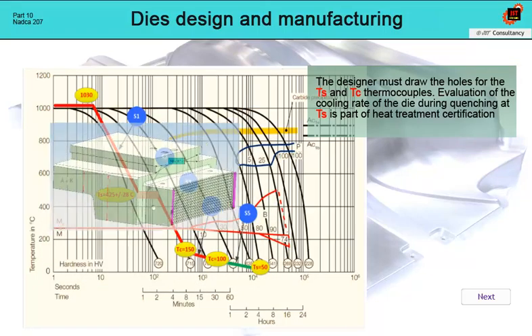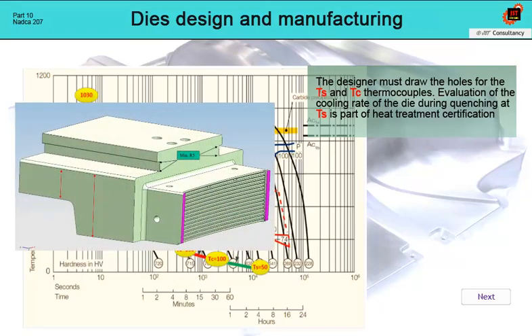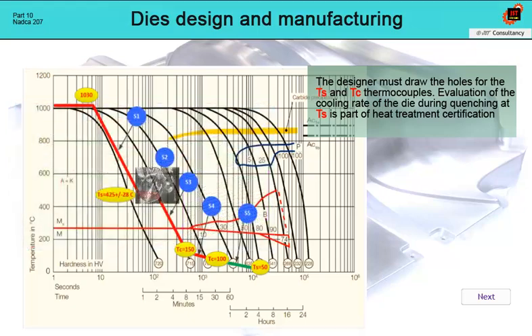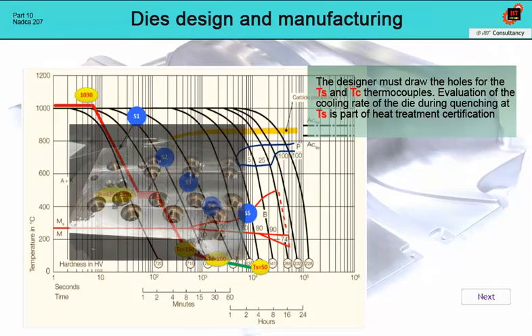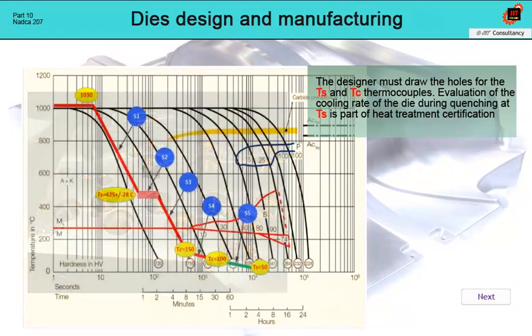In order for this to be implemented in practice, it is recommended to create a special process drawing for the machining of the die for quenching. The method of machining before hardening should ensure adequate surface quality so that there are no places with notches, generating possible high tensile stresses. The designer should also take into account the positions of the individual holes for the ejector pins in relation to the cavity itself, so that there are no significant transitions in mass.